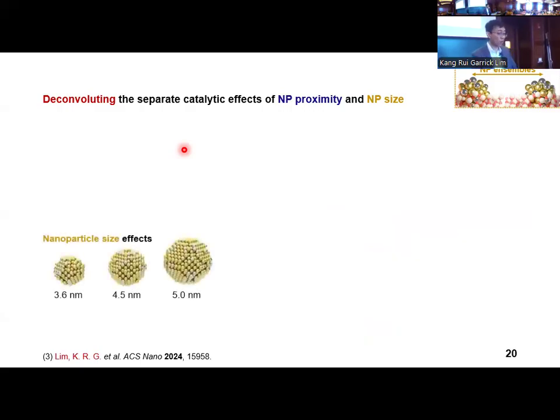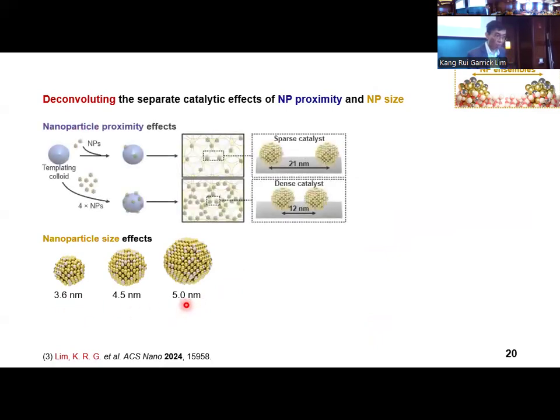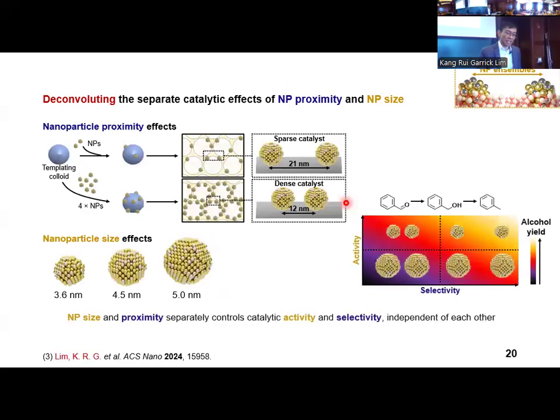After learning that nanoparticle proximity controls selectivity, the next natural question to ask is, what about the effects of nanoparticle size? Since the RCT platform uses pre-synthesized colloidal nanoparticles, we can easily change the nanoparticle size while maintaining a preset ratio of nanoparticles to templating colloids to keep the interparticle distance fixed at 21 or 12 nanometers. I will not have time to elaborate on this work, but our key takeaway is that nanoparticle size controls activity, while nanoparticle proximity controls selectivity, separately and independently from each other. Therefore, we maximize the desirable benzyl alcohol yield using catalysts with smaller nanoparticles separated by larger interparticle distances to overcome trade-offs between activity and selectivity.